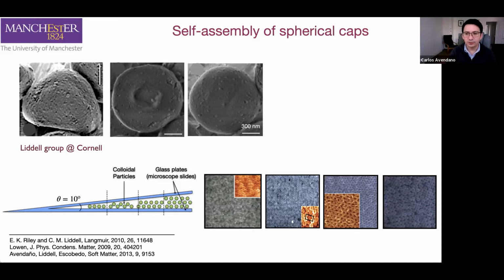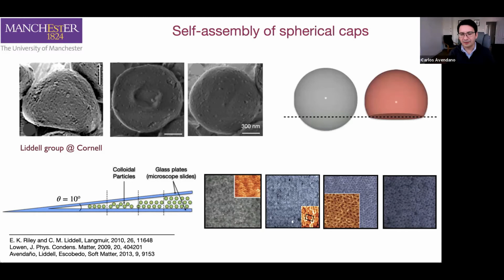So for that, we need obviously a model. And the model that we decided to use was a very simple one, albeit a little complicated to model. We took a hard sphere, so a particle that doesn't have any attractive interactions. But then we took the particle and we cut the sphere at a certain height. So you can see that the resulting particle has the main features of the experimental system. It has a spherical section on the top, but at the bottom, it has a flat facet. And we use that model to try to represent the experimental system.